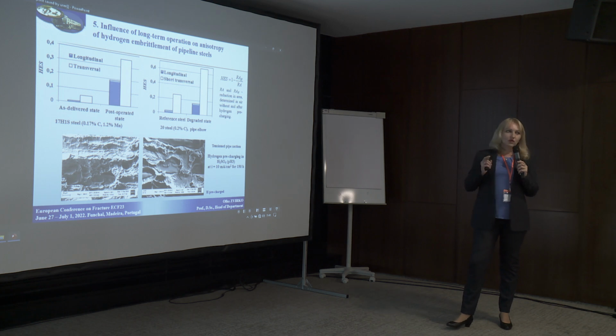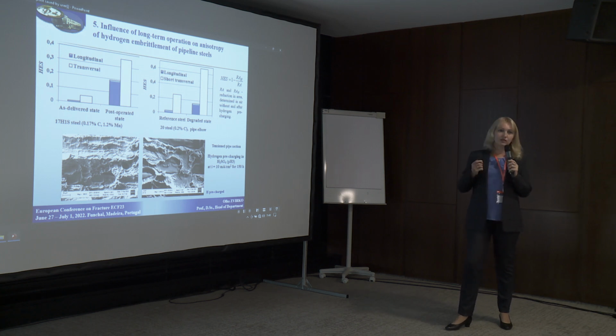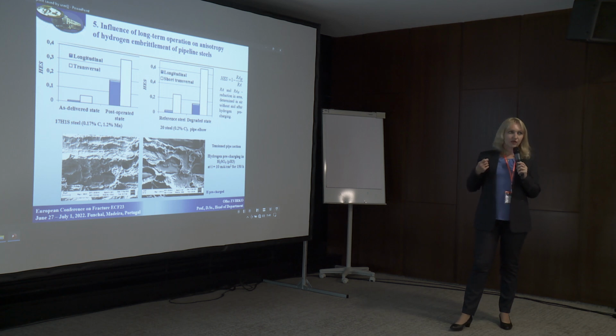I'd like also to emphasize that hydrogen embrittlement susceptibility of the degraded steel is the highest when the fracture propagates along the rolling direction, indicating the weakest cohesion in this direction. So it's also maybe the main reason for development of in-bulk delaminations in pipeline steels.